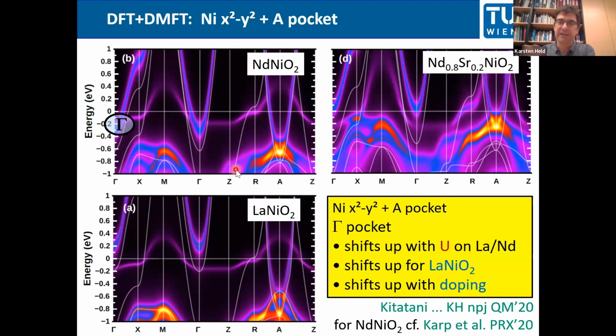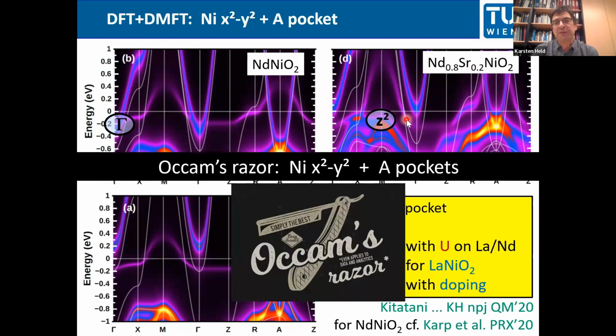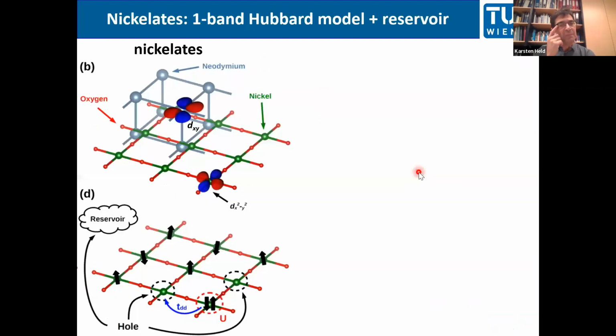If we follow that, from our DFT plus DMFT calculation, you can also see the z-squared orbital. It's here in the superconducting regime still below the Fermi energy. If you dope it more to 30%, it crosses the Fermi energy and you get multi-orbital physics. But in plain DFT plus DMFT, you don't get multi-orbital physics in the superconducting region of the phase diagram. And with that, our approach is: let's make the most simple, most fundamental model for the nickelates and take Occam's razor to simplify it as far as possible, and then we just have one correlated orbital, x squared minus y squared, plus these A pockets. It even becomes a little bit better because the A pocket is made up out of this neodymium xy orbital.